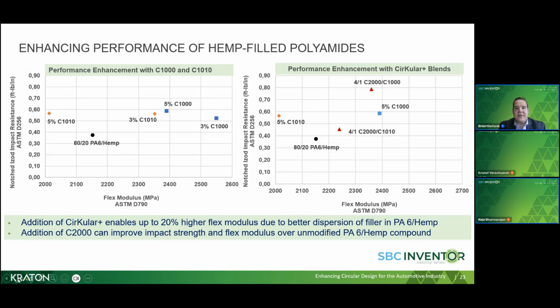So with the C1000, we get the synergistic improvement in impact and stiffness at both the 3% and 5% level. Normally when impact increases, stiffness decreases, but we only need a small amount of the compatibilization series to achieve higher impact and also improve stiffness. Now on the right-hand side, you see the effect of a hybrid system, where a small loading of our compatibilizer series combined with the performance enhancement series can be used to further optimize impact stiffness balance. So the hybrid system is really just another tool to help you meet your performance specification goals.